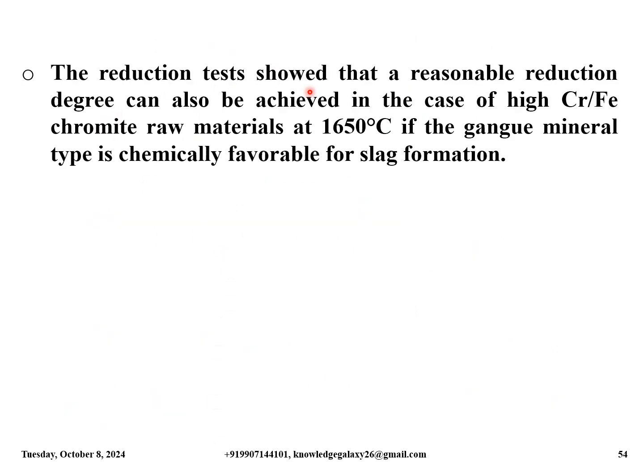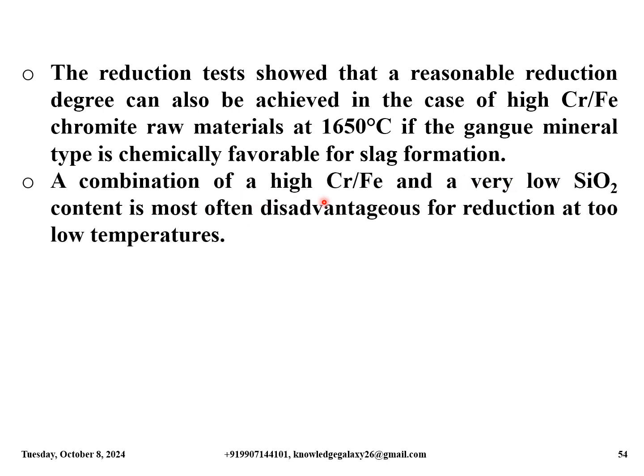The reduction test showed that a reasonable reduction degree can also be achieved in the case of high Cr/Fe ratio chromite raw materials at 1650 degrees Celsius if the gangue mineral type is chemically favorable for slag formation. A combination of a high Cr/Fe ratio and a very low SiO2 content is most often disadvantageous for reduction at too low temperatures.